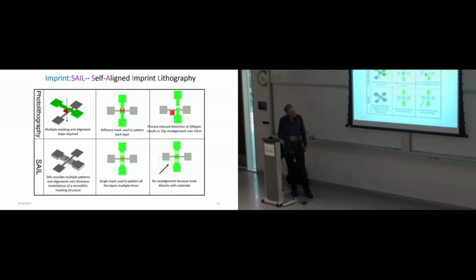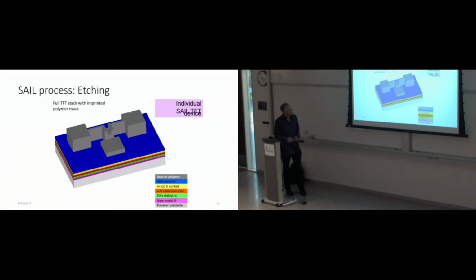So what we do is we encode the different information in different heights, and I'll go into more detail, but everything deforms, and it deforms uniformly, even though this deformation is actually inhomogeneous. It's not just an affine translation. In some places where the metal is bigger, it has a different expansion, so it's actually a nonlinear kind of thing. This is the self-aligned process, and this is our contribution to the whole thing, as well as just getting things to work.